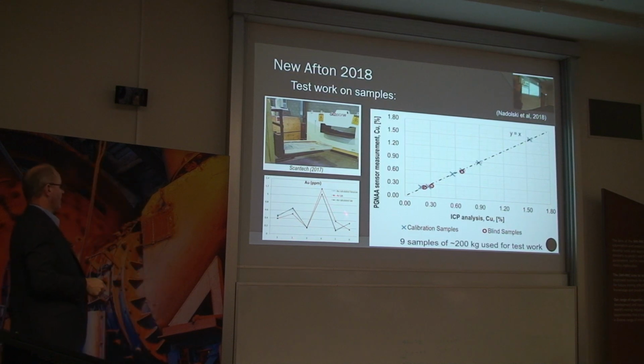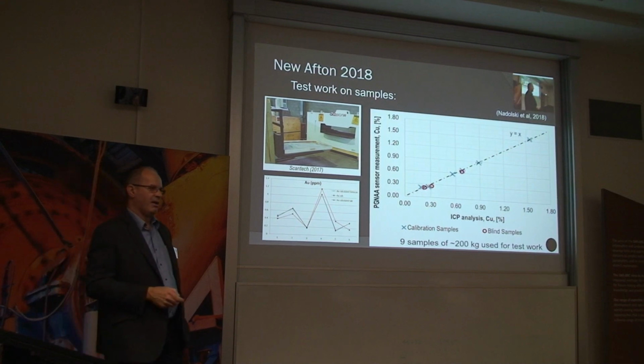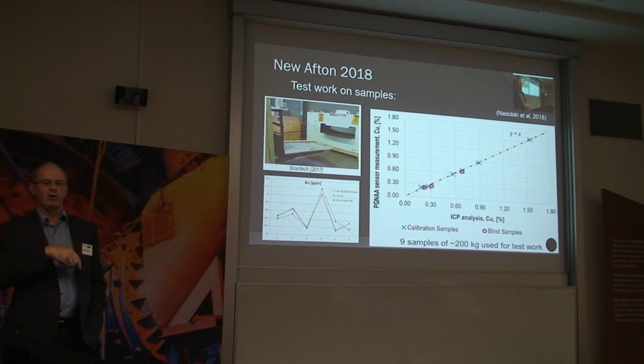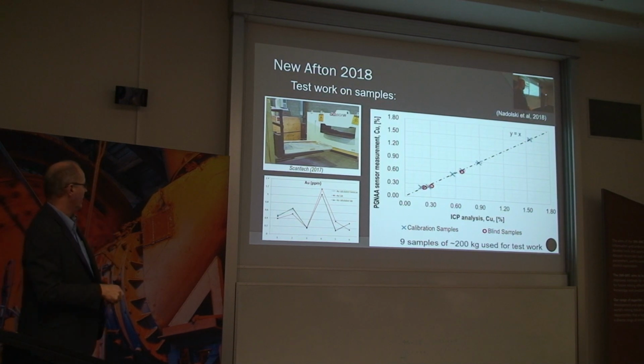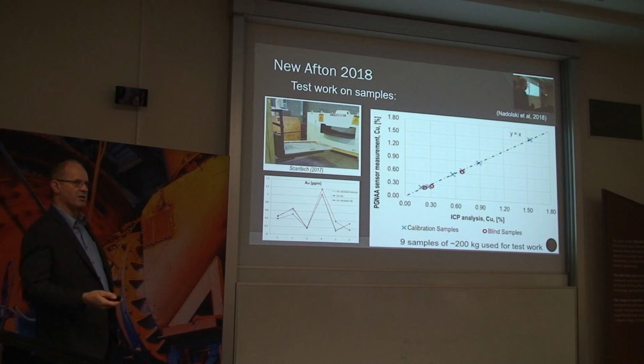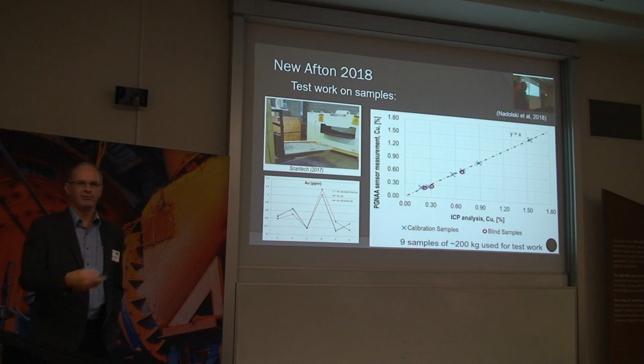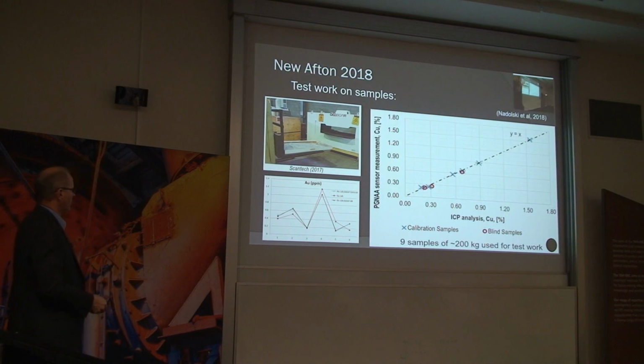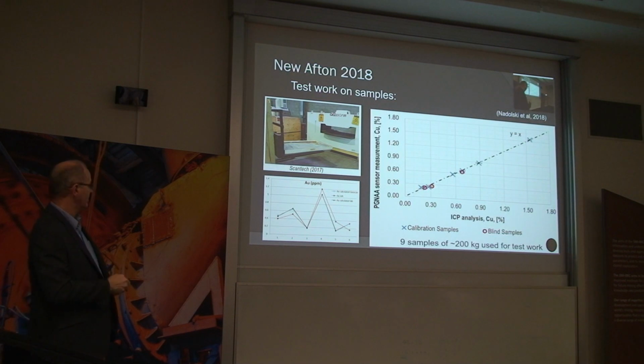Interestingly, there's a gold graph there. We were able to calculate gold from the copper and sulphur. Now, they had calculated the gold themselves using their lab data. The lab data was the red lines. Their calculation of gold was the dark blue, and calculation of gold from our analyzer results was the light blue. And I guess the reason we're so close to theirs is because we used their formula to calculate the gold from the copper and sulphur. So that demonstrated a reasonable estimate of the gold grade.